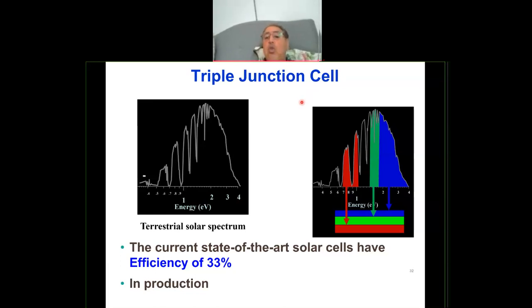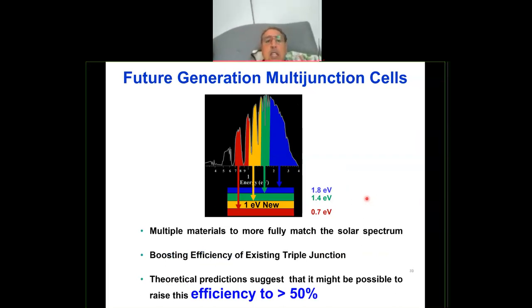But of course, we want to go to the 4th-generation solar cell to increase the efficiency even further. So this is what the future generation multi-junction solar cell looks like. In the existing one, we use, for example, a semiconductor which has got 0.7 EV, like germanium. Here, 1.4 EV, I show you as well, so some indium gallium arsenide, and then some 1.8 EV. So these are the energies of the semiconductors we use to absorb. But as you can see here, there's one energy missing, for example, 1 EV.